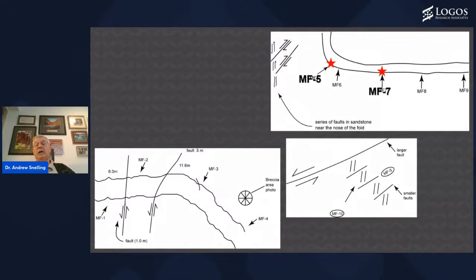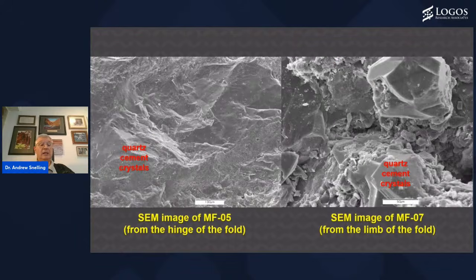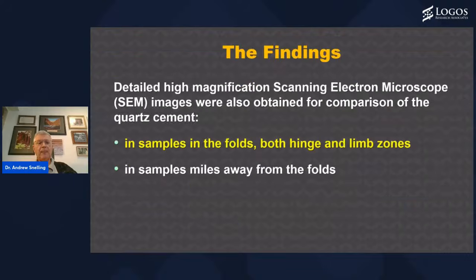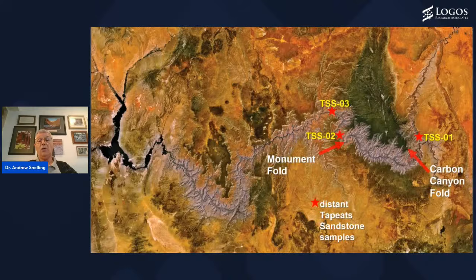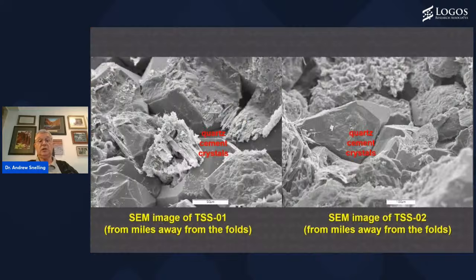Compare hinge zone and sample 5 with limb zone sample 7. Again, quartz cement crystals have pristine faces and terminations as the crystals grew into the pores within the sandstone. And then we looked at samples miles away from the folds. Were they any different? Was cement any different? No. Let's look at these distant samples.